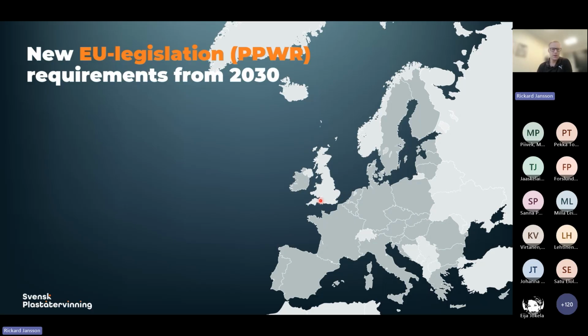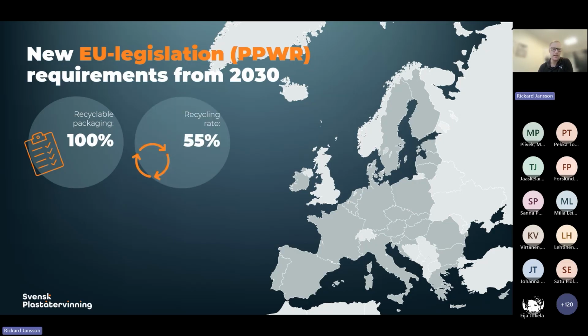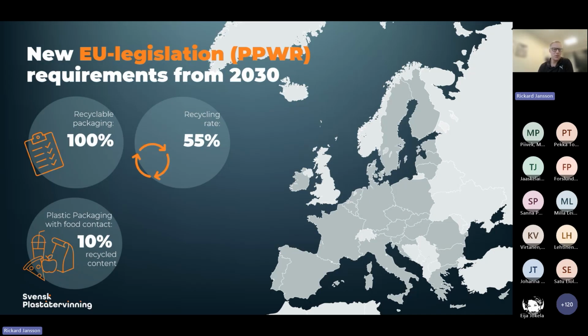Looking a few years ahead, you know that the new packaging and packaging waste regulation will soon enter into force, and there are requirements that at least from 2030 will have a great impact on the plastic packaging industry, since it requires that all packaging from 2030 must be recyclable. And that we should be able to recycle at least 55% of the plastic packaging that is put into the market. And we also must use the recycled materials back into similar applications again. So for food contact materials, we should use at least 10% recycled materials. And if they are made of PET, it's even up to 30%. And for other packaging applications, which are not contact sensitive, 35% of recycled materials are expected to be used.